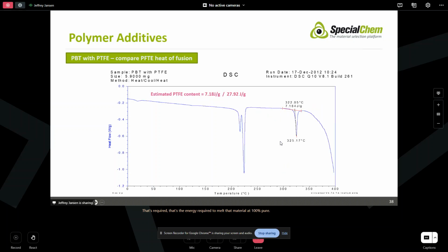Okay. When we have our PBT-PTFE mix, we can see that here we've got about 7 joules per gram, which would suggest that we've got roughly 25% PTFE in that PBT. Now, there are other ways to come at this. TGA would be a great way to analyze this also, but again, it's another piece of information that you can get off of the DSC.